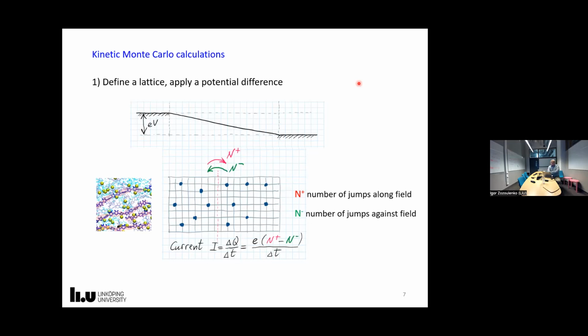Okay, and to answer this question, Monte-Carlo calculations have been performed, and here I will briefly describe the main steps. First, we simplify our system. Instead of this very complex geometry, we define a lattice, a square lattice in the simplest case. Then we apply a potential difference, and we put particles which represent polarons, which jump over this lattice. To calculate the current, we simply count the number of jumps along the field and against the field.